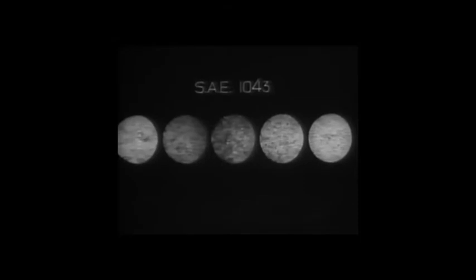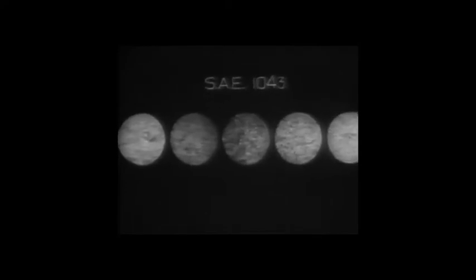What has happened in this process to change the properties of the steel? Here are 5 micrographs of an SAE 1043 steel, which show its structure after tempering at progressively higher temperatures. In each stage pictured here, the steel is tougher than in the previous one. The first micrograph is of the fully hardened steel. It shows the typical martensitic structure of plain carbon steel at maximum hardness. The steel's Rockwell C reading, the measurement of its hardness, is very high, 60. On the other hand, its Charpy reading, the measurement of its toughness, is very low, 3.